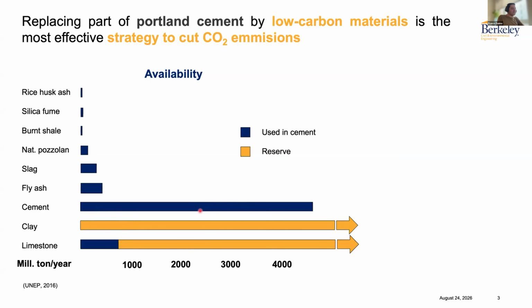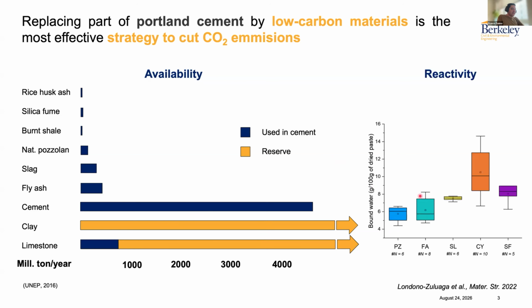Now, what we have available in the crust is clay, it is not calcined clay. There is still a gap that we need to fill with investment and with industrial adoption in order to make that clay resources that are available in the crust into reactive and processed calcined clays that we can use. And what makes calcined clay so interesting is really the reactivity, right? So this is something that we can measure with a standardized method like ASTM C1897, and we can see that overall calcined clays, in this case CY, are way more reactive than the other materials, and down the line that reactivity translates in the ability we have to reduce clinker further without compromising performance.